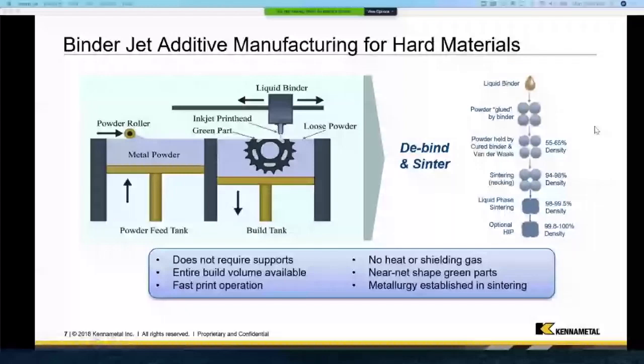In the sintering operation, as you go up in heat, you get consolidation and densification of your component. You can achieve 98 to close to 100% density just following liquid phase sintering, and then we can get to a full 100% densification, if not through sintering, by a follow-on hipping operation.